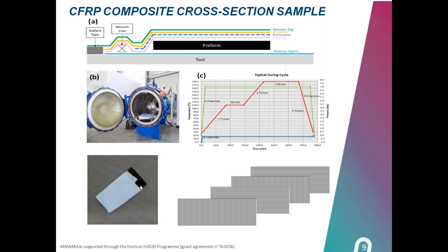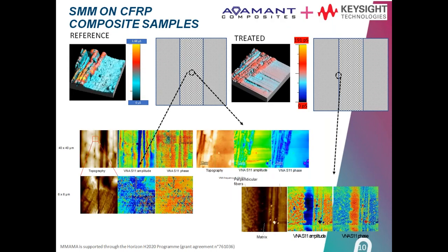Here are the composite samples that we produced, and then we did some investigations with the partners to see what happens in their cross-sections and get some good insight of how our doping process improves the properties of the material. So with Keysight, we did some SMM where we could see also the topography of the sample, but we were also able to map the conductance. And here we see the difference between a reference sample where we don't have any dopants and a treated one where we have the dopants.